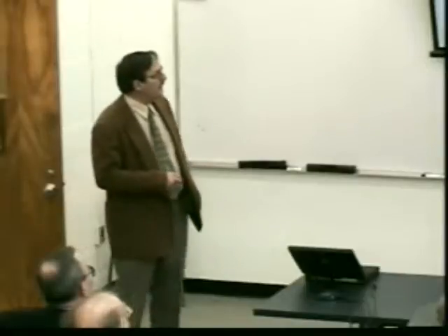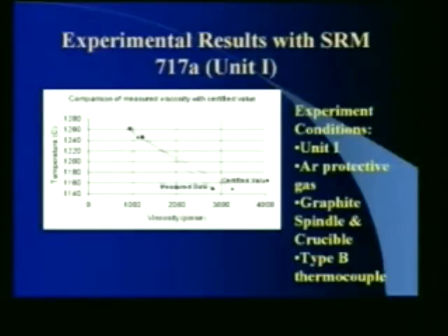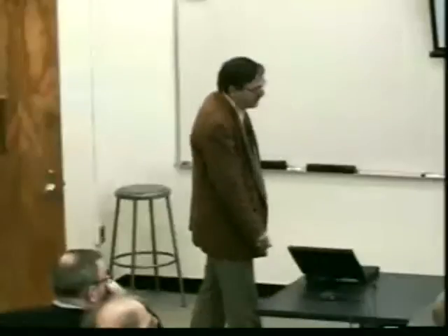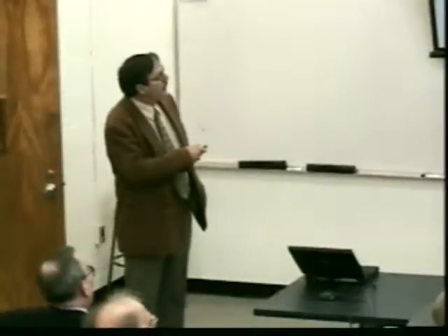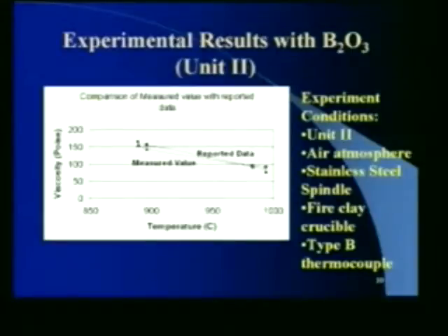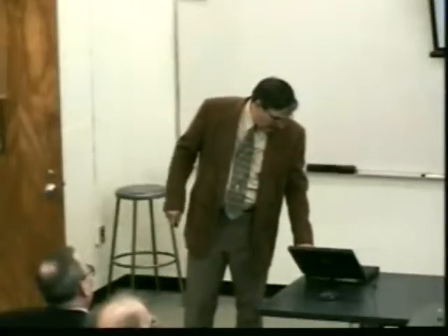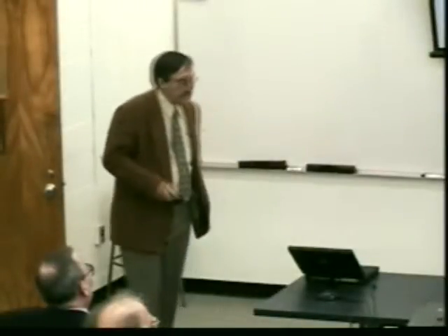In order to be able to determine whether or not your viscometer works properly, of course, you have to calibrate it. And there are ASTM standard glasses that one can purchase that the viscosity is known. And this is just an example of a viscosity in poise versus temperature in degrees centigrade, where the measured value from our viscometer versus the certified value is shown. This is over a temperature range of about 1260 to 1140 as an example of calibration. And this is another lower temperature calibration with boron oxide, which is pretty well known, where the viscosity and reported values are shown in the temperature range of 900 to 1,000 degrees. We'll look at some of the measurements for the real system in a minute.